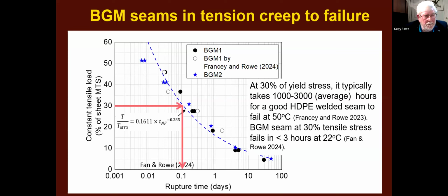Now, why did we pick 30%? Because we all know that HDPE suffers from stress cracking. And the stress crack test is done at 30% of the yield strength. And we have done quite a lot of tests on welds and found that the welds typically crack, depending on the material, depending on the quality of the weld, between 1000 and 3000 hours for a good HDPE weld. At 50 degrees C in a surfactant solution.